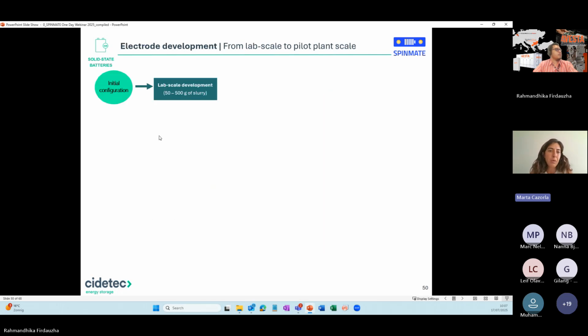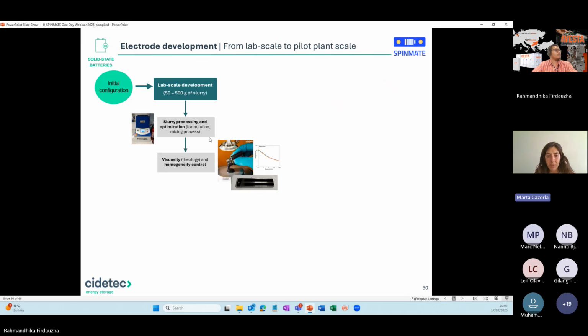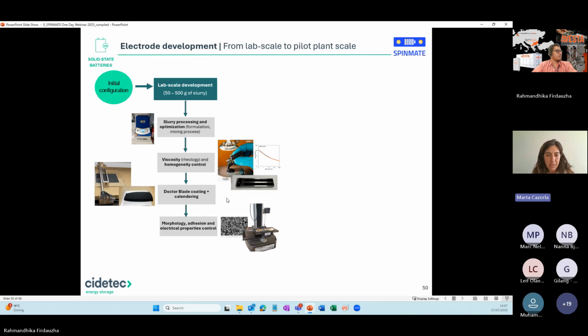How does this go? From our initial configuration, we do a lab scale development. This is around 50 or 500 grams maximum of slurry. So this slurry we process, we optimize it, and then we characterize it. It's very important to control the viscosity and the homogeneity of this slurry for a proper coating. Then we do it at small scale using Dr. Blade equipment. And we calender these coated electrodes, and then we see their morphology, adhesion, and electrical properties, and then we do electrochemical testing at a small scale.